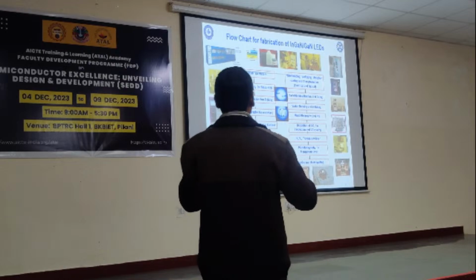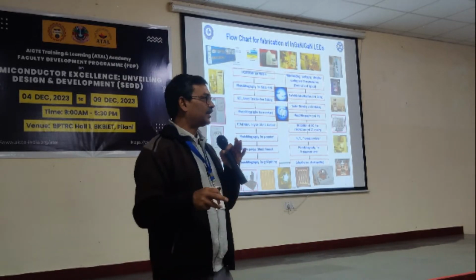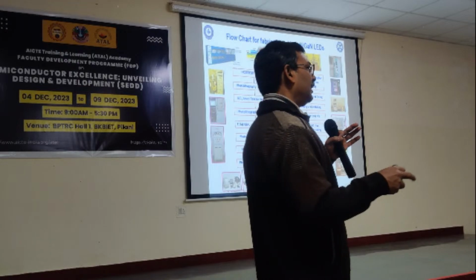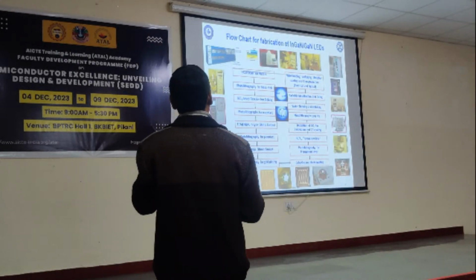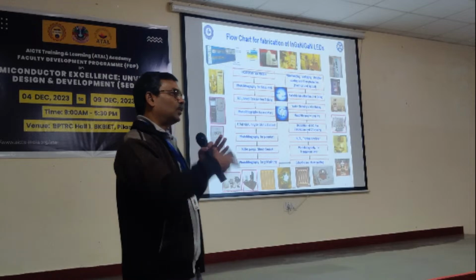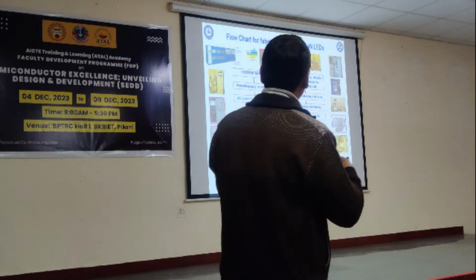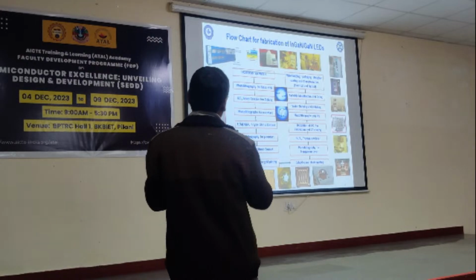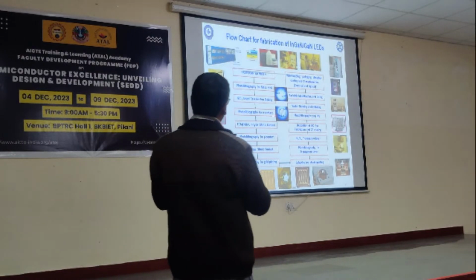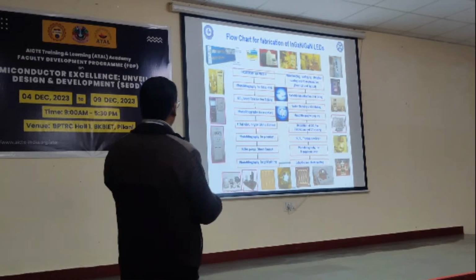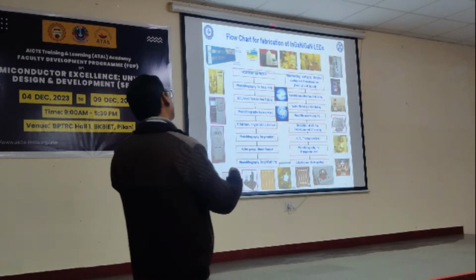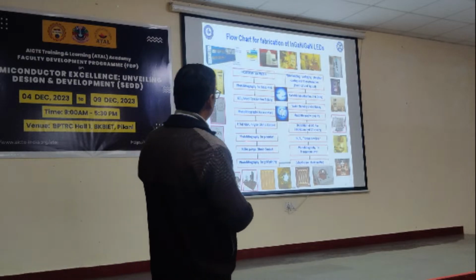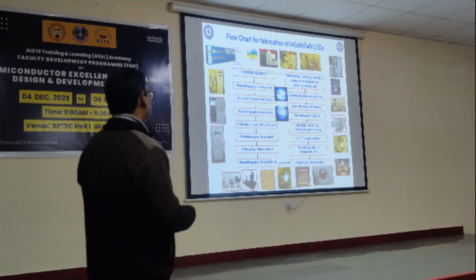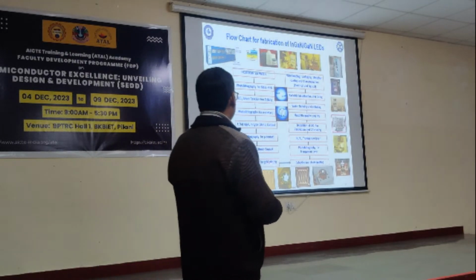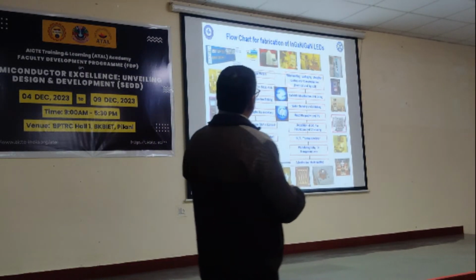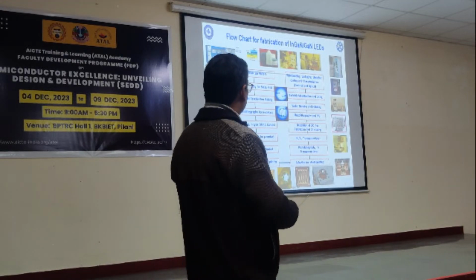After etching the N region, we go for contact formation on the N side, so we can get the N contact. Again, we have to go for further photolithography for a selected portion of the P, for the P contact. So various sections are there. Photolithography for N contact, then titanium, aluminum, nickel, gold N contact formation, then annealing for ohmic contact, then photolithography for P contact, then another nickel gold P contact formation, then photolithography for gold plating. Then after that, we go for dicing.